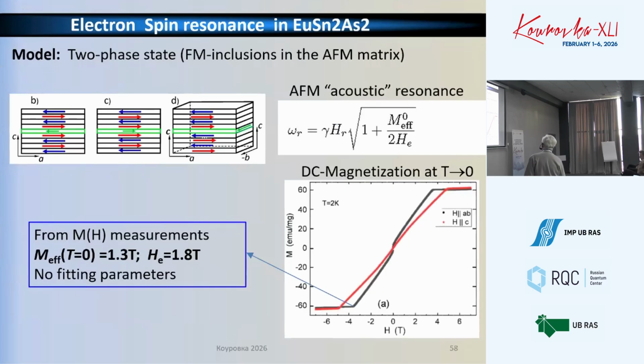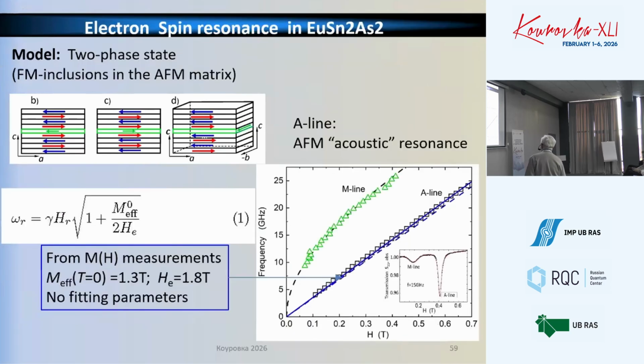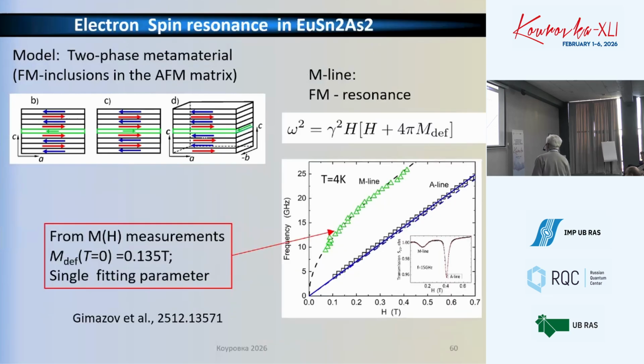With the antiferromagnetic acoustic resonance, nothing changes. We have here all parameters known from the magnetization curve, no fitting parameter. We can fit our measurements of the field dependence of the resonance line with no fitting parameters. As for the unknown line, which we now attribute to ferromagnetic resonance in the antiferromagnetic crystal, we apply the textbook behavior. There is one parameter, which is the magnitude of the magnetization of the defect layer in our case. It can be taken from experiment or used as a fitting parameter. They're comparable, but we prefer to use as a fitting parameter a value 10 times smaller than the antiferromagnetic magnetization.